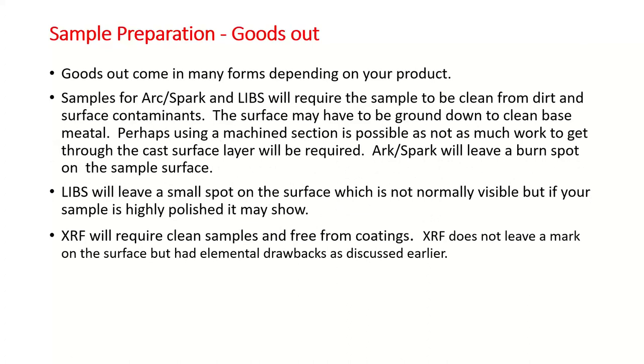Again, goods out, I think we really covered this, but basically if your sample requires testing, then you need to be able to test on a point that is clean. The surface may need to be ground. ArcSpark and LIBS will need the surface to be cleaned, especially on a casting surface, because sometimes you'll get contamination from the outer or the coatings that were around the casting in the mold. And that may give you strange readings and make a difference to what you're actually measuring.